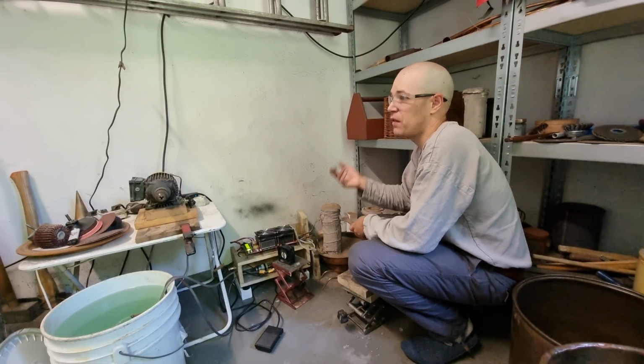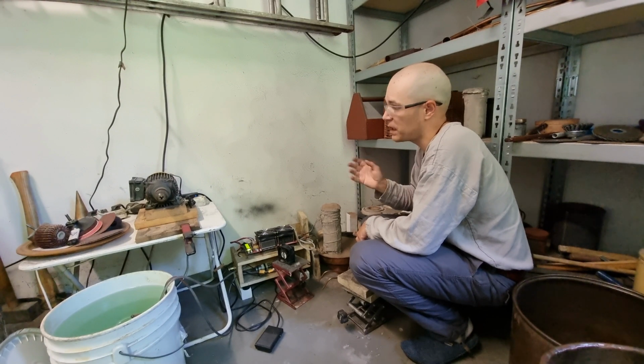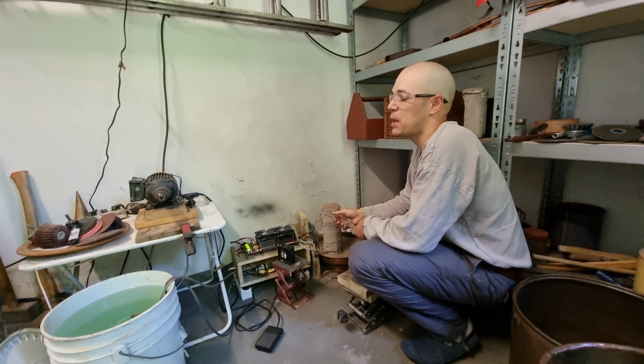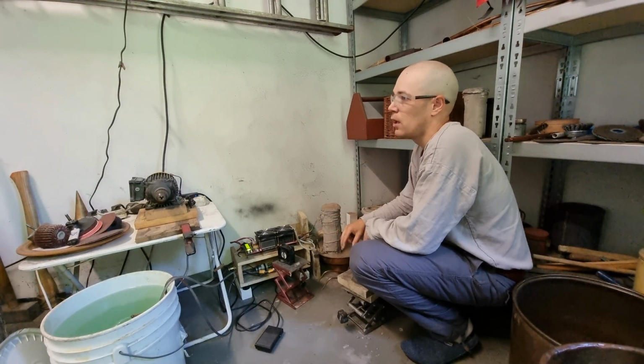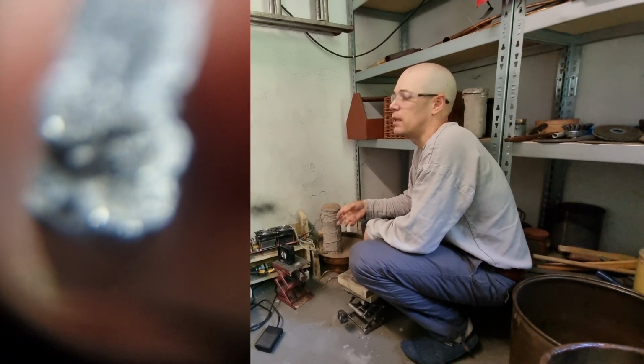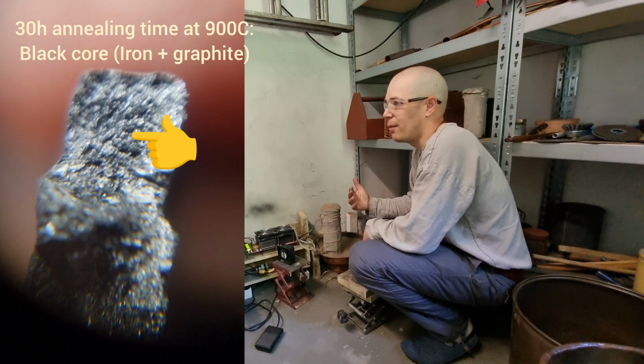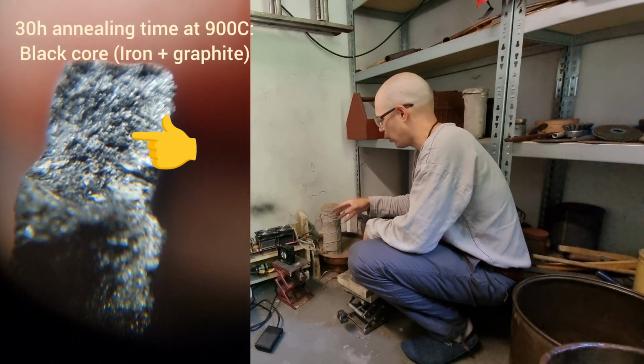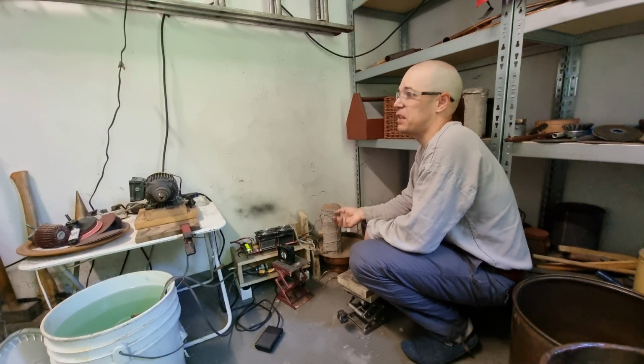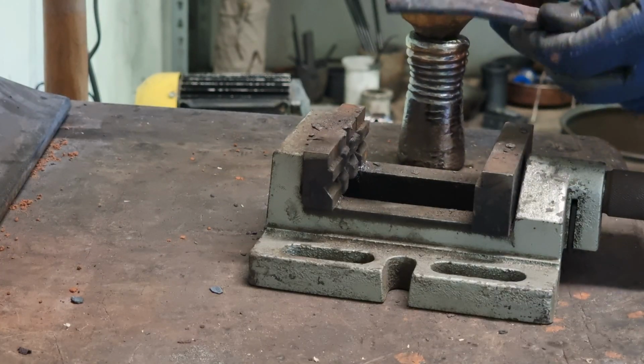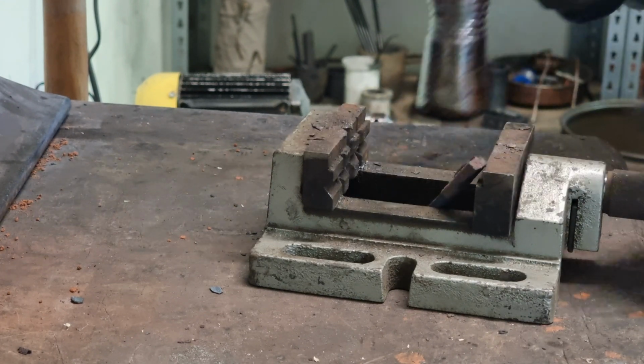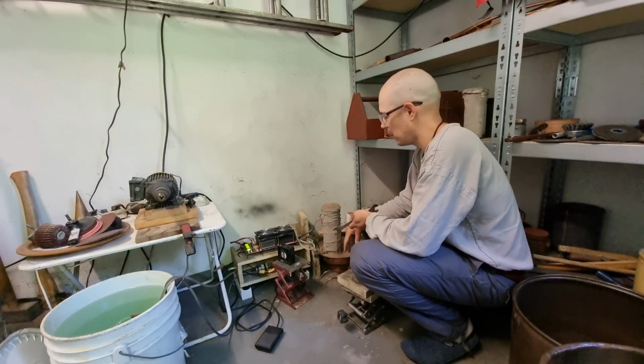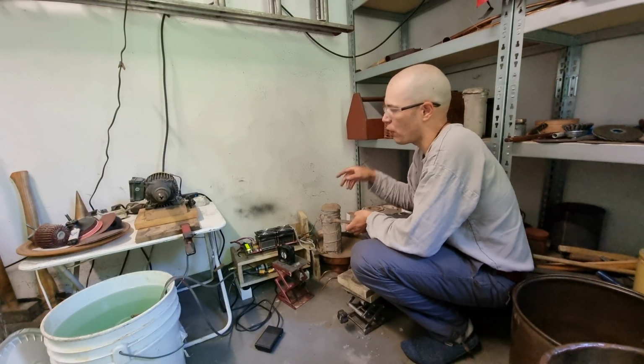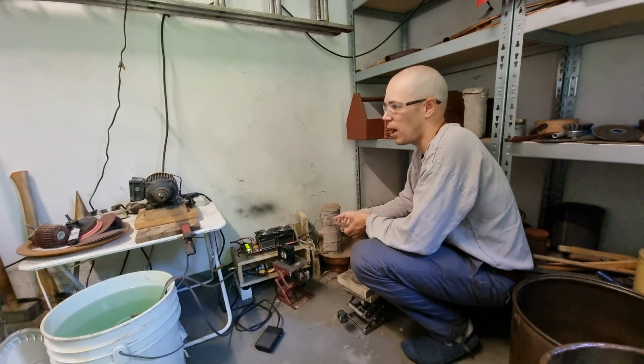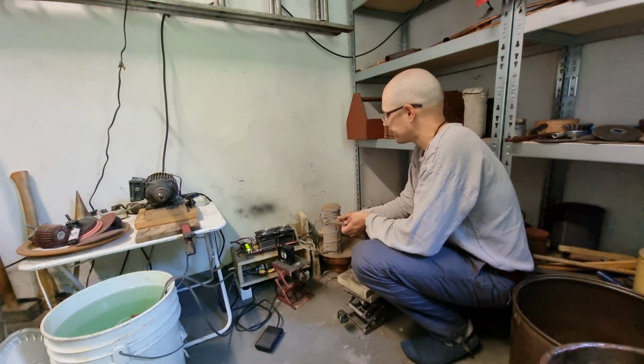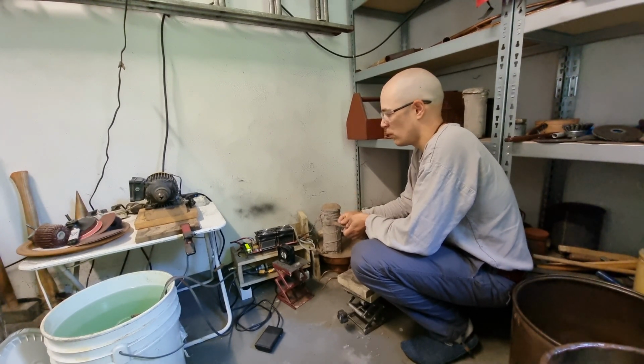If we promote this process even further, if we let it run for 24 or 30 hours, we really see that more and more of that carbon gets separated from the iron, and we convert the white cast iron to the so-called American cast iron, which is black heart malleable cast iron, where we got a good separation of carbon from the iron, and which is now malleable cast iron, which is really bendable, much more tough and durable than cast iron, white and gray. So that is really the trick about that annealing process. That was the technique of making useful materials out of white cast iron, just by this heat treatment.